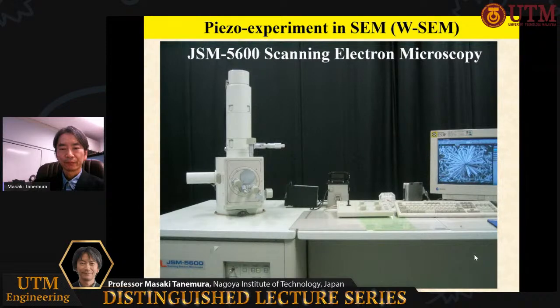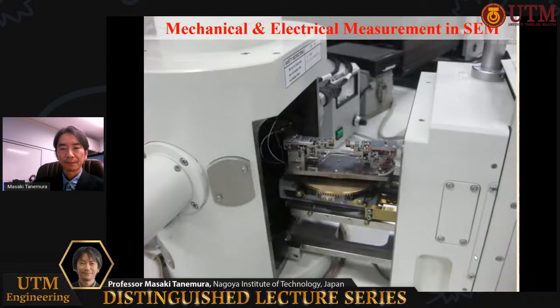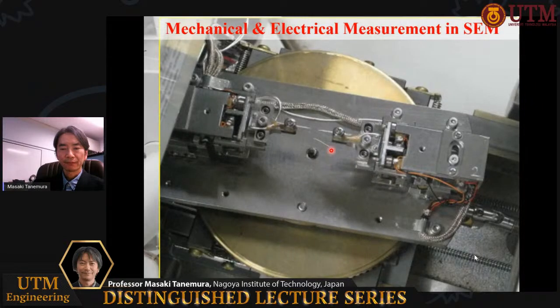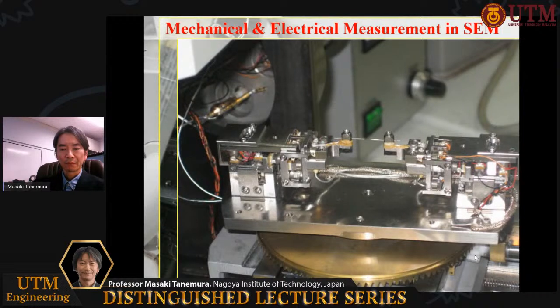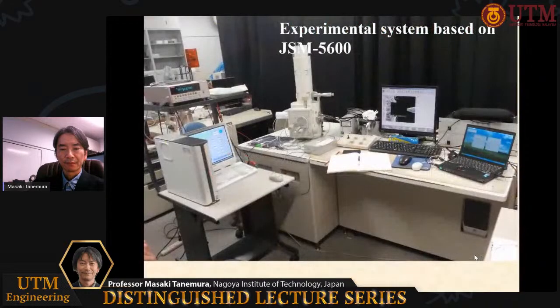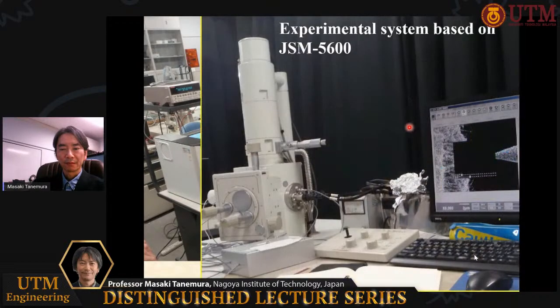But first, we will check the mechanical property. For this purpose, we use a scanning electron microscopy (SEM) system. Two probes are installed in the conventional SEM system like this. This is the top view image of the probes. The carbon nanofiber sample is attached to one of the probes, and the counter electrode is attached to the other probe. The motion of the probes is controlled by piezo. This is the system assembly. We can also measure the electrical property of the sample using this system. We can select the sample position by observing the SEM image like this.